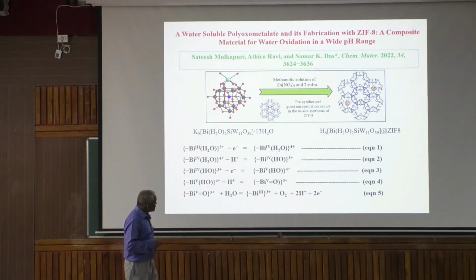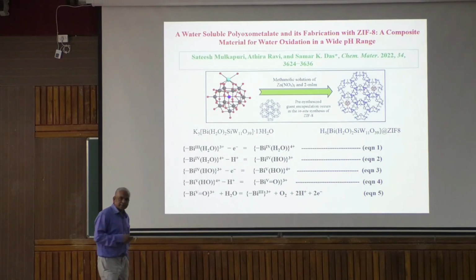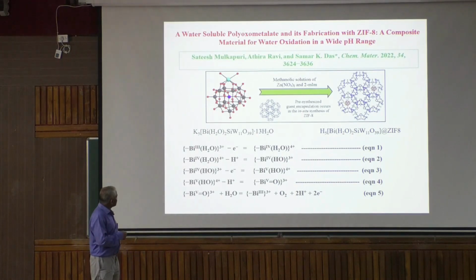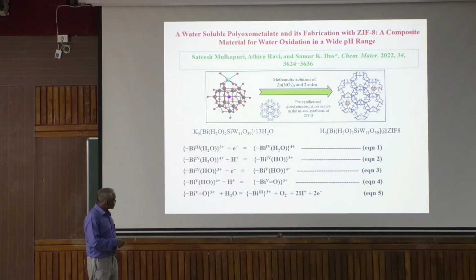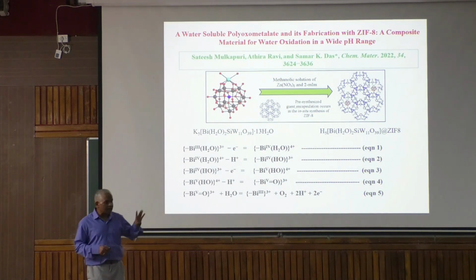And why did we do that? Because with this bismuth, as inorganic chemists, we know that bismuth 3, if you start, can go up to bismuth 5 also by 2 electron oxidation, and that is very active towards water oxidation. It will oxidize water, come back to bismuth 3 and oxidize again. So having that idea, we encapsulated it there. Why encapsulate, I told you?